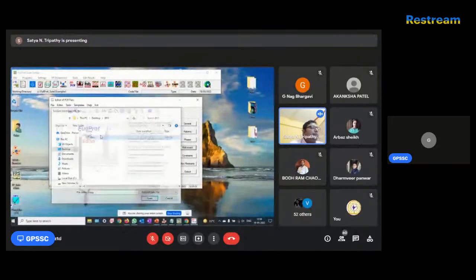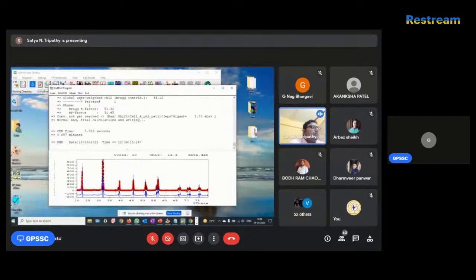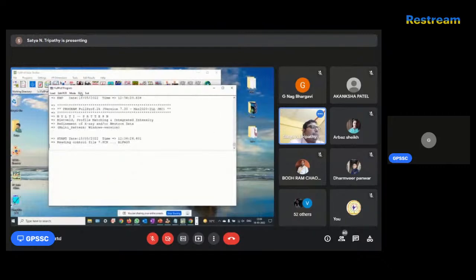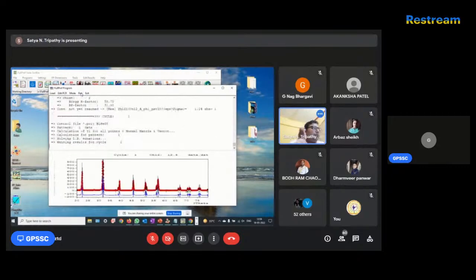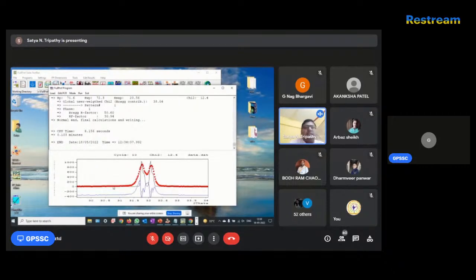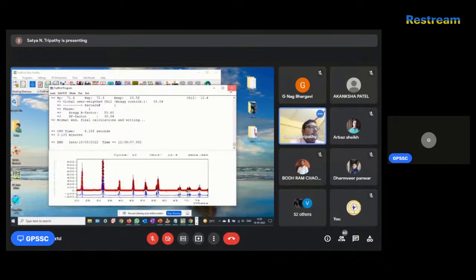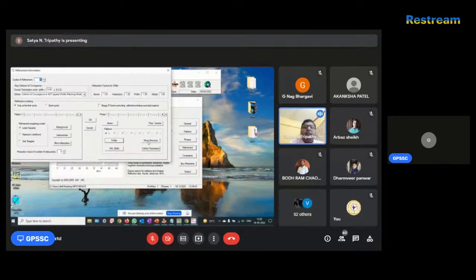So what you need to do, for better peak position, you can refine the lattice parameter. So let me first define the lattice parameter. There will be a little bit of change if we do that, because it will adjust your experimental value to the theoretical value. It is fine, no problem. So you can see that lattice parameter is now refined, right? I close it. Then I go to the peak shape. Peak shape is X and Y. If you do that, you can see that the lower end of the peak will be fitted. So this is okay.